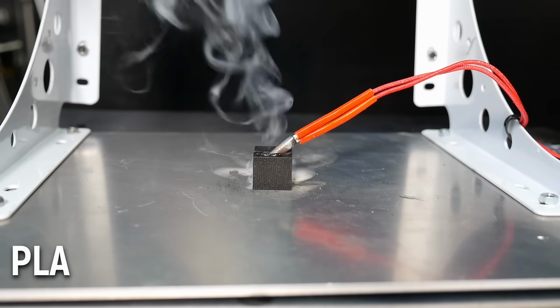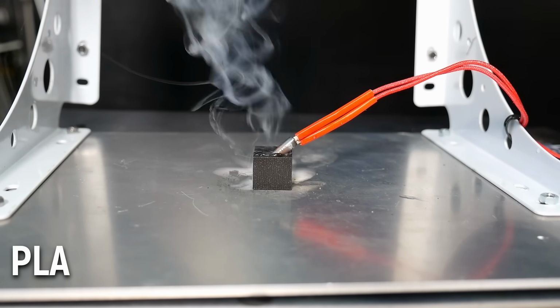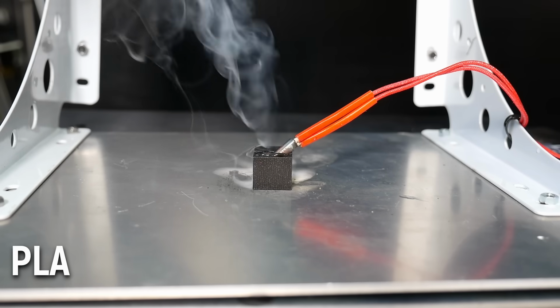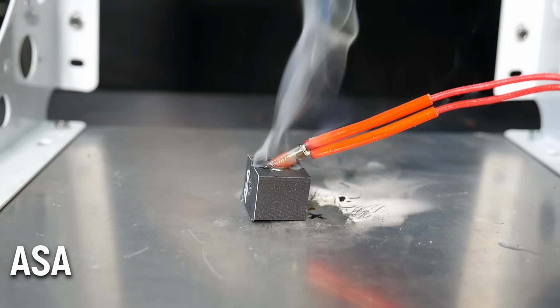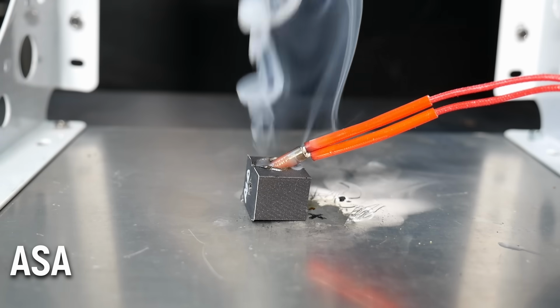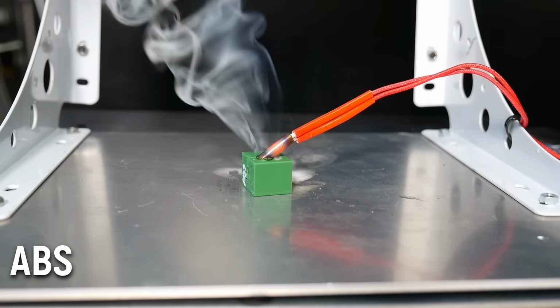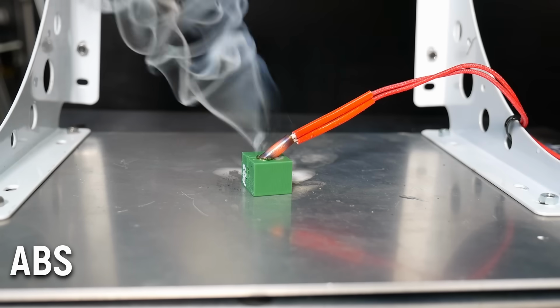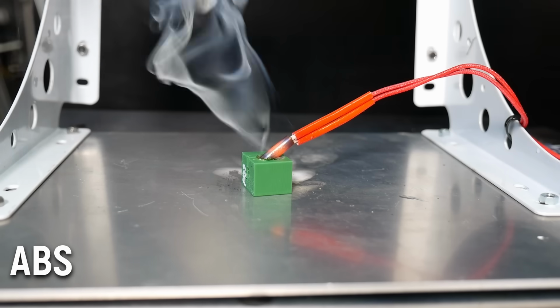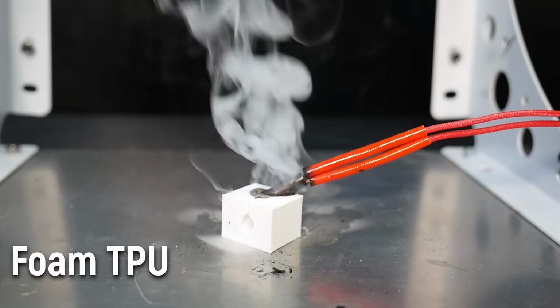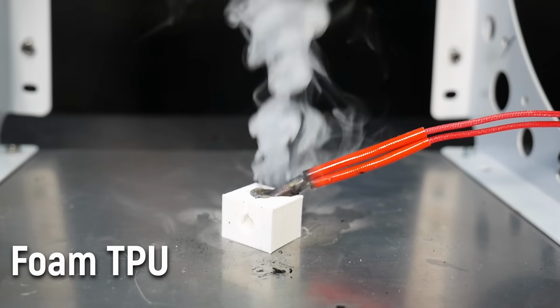All of the test samples made plenty of nasty smoke, though I would say not as nasty as when they were physically burning, but the heat cartridge did get up to a dull red glow, which means it was well above the 400 degrees Celsius or so that you would theoretically need to autoignite at least some of these filaments. But alas, even the foam TPU didn't autoignite.